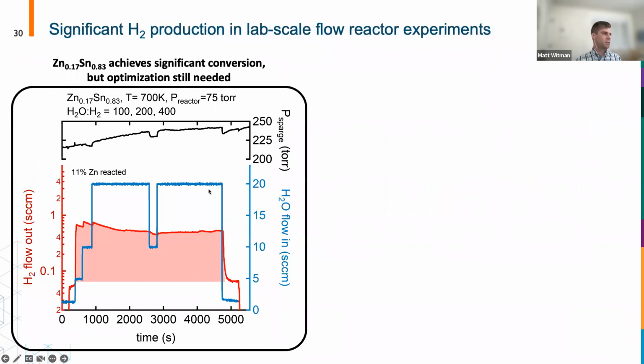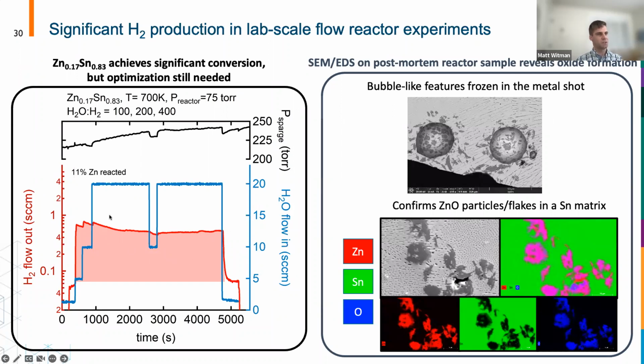So my collaborator, Tony McDaniel, is the experimental expert on all this stuff. He actually went into lab and started off with this off-equimolar zinc tin alloy, and was able to achieve significant hydrogen conversion in this flow reactor, where he sparges in steam at different input water to hydrogen ratios. That's the different steps you see here in this blue curve. So he's feeding in gas at the same pressure, but changing the steam to hydrogen ratio. And you can see that the hydrogen production above the baseline, the red integral under this red area, is kind of constant as a function of the steam to hydrogen ratio. But over the course of this experiment, he was able to convert 11% of the zinc to zinc oxide.